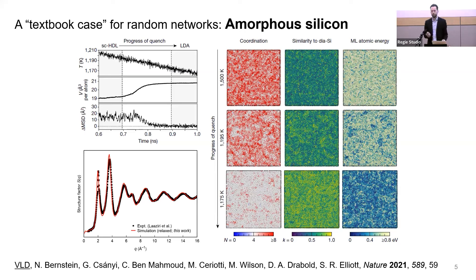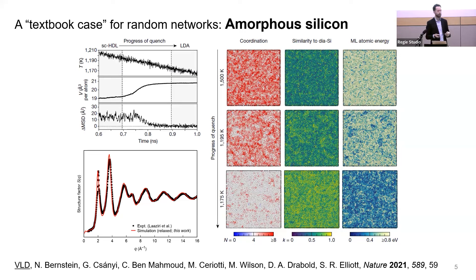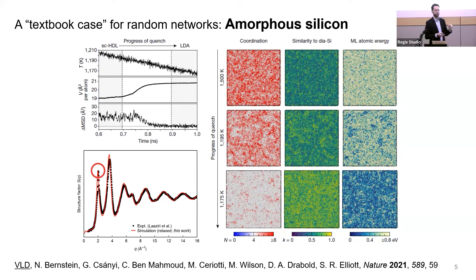We can analyze the structural properties as it becomes more similar to the diamond-type structure and locally more favorable where solid regions form. We spent quite a lot of time checking that the simulations are valid. The experimental fingerprint of ordering in this amorphous structure is the structure factor, and specifically the first sharp diffraction peak — its height is very closely in agreement with experiments, which gave us confidence that these models are accurate and reliable.